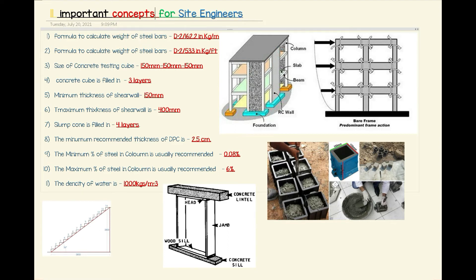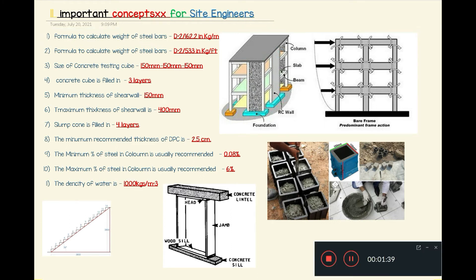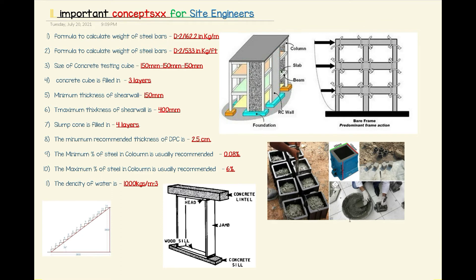The cube is filled in three layers, and every layer has to be hammered 25 times with a rebar so that there are no pores, holes, or air particles left within the concrete. This is a very important point for site engineers to remember.